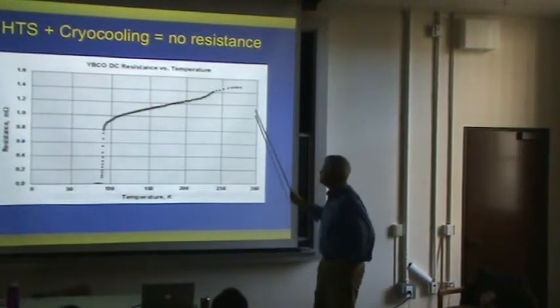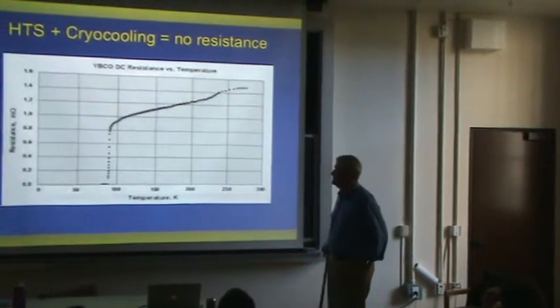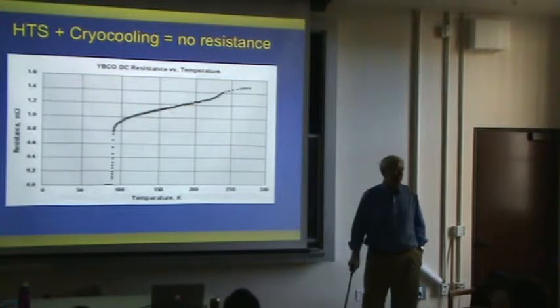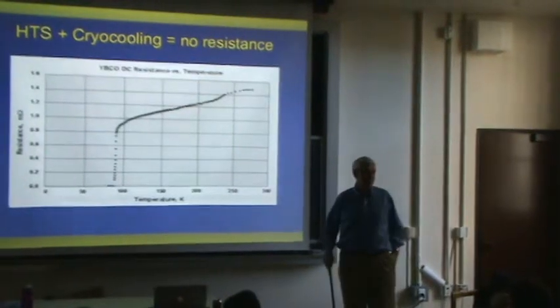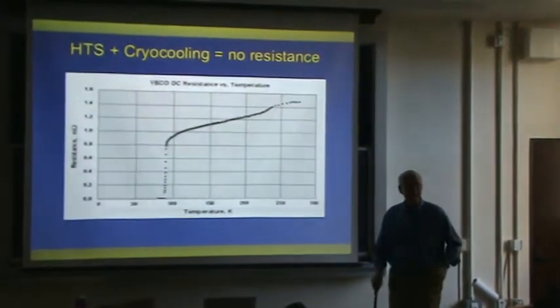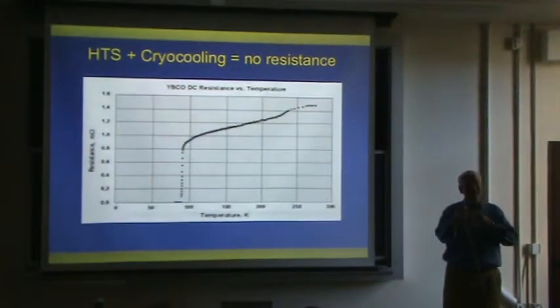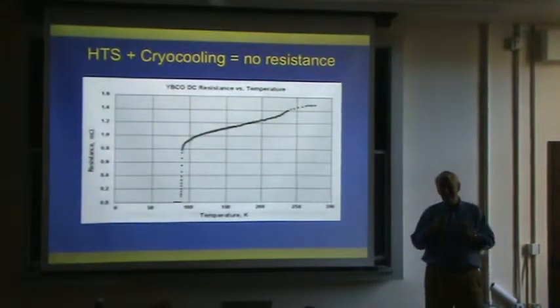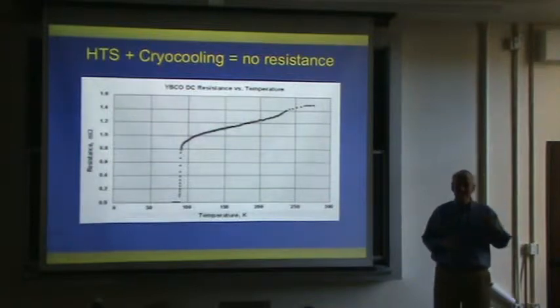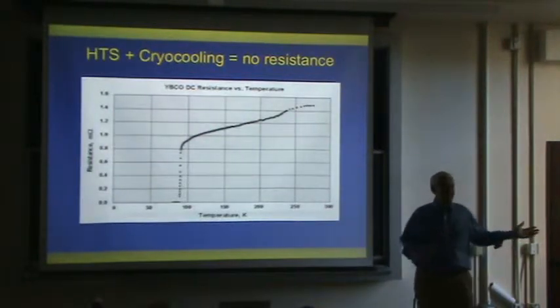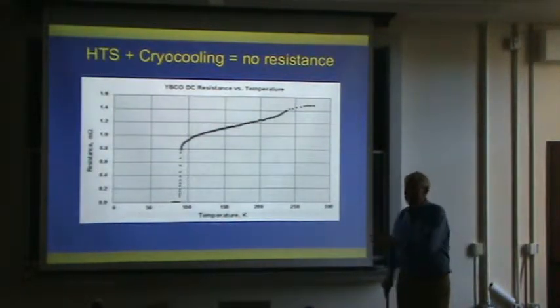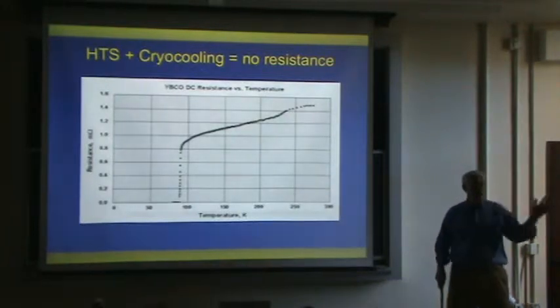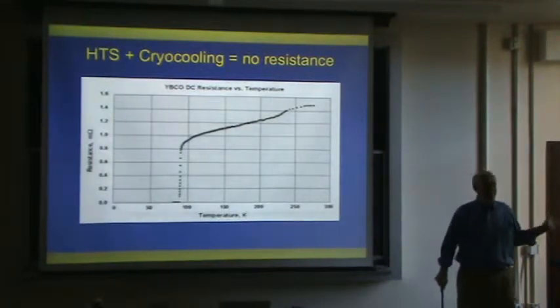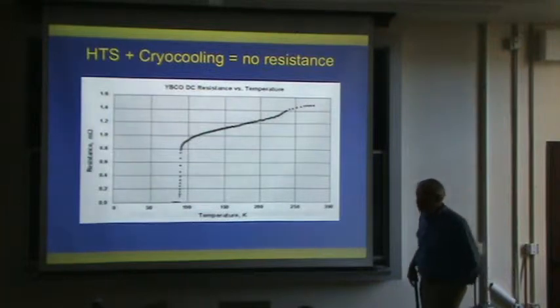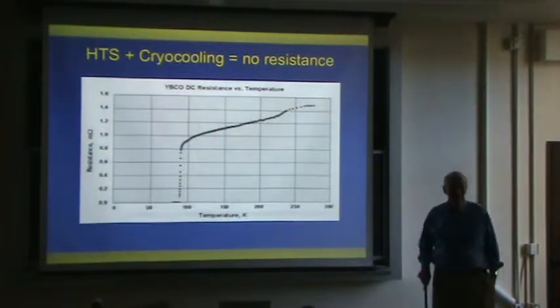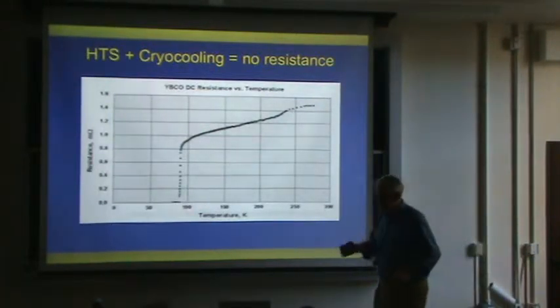And this was really historic, but they discovered that this became superconducting at above liquid nitrogen temperatures. In fact, it gets up to 97 degrees Kelvin. So any way you tried to take the conventional theory at that time, distorted it a little bit, you couldn't explain it. Transition temperature was up near 100. So at that point, with this discovery, everyone recognized that this was completely new for them. How new? Even then, people didn't know, actually. It's new in a profound way.